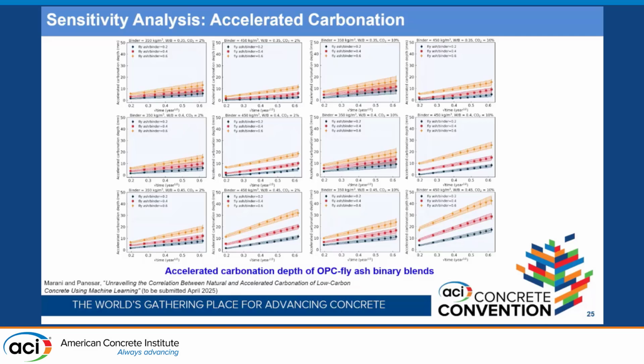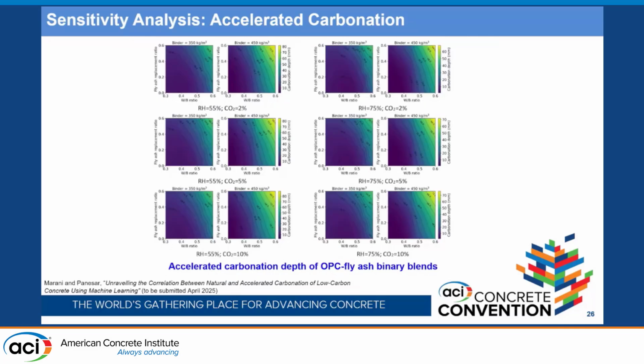As you can see, if we increase the level of replacement, the carbonation depth goes up, which is in good agreement with the findings in the literature. And you can see that we can capture this effect across different types of mixture design parameters. Here are heat map graphs that show the interplay between different parameters.